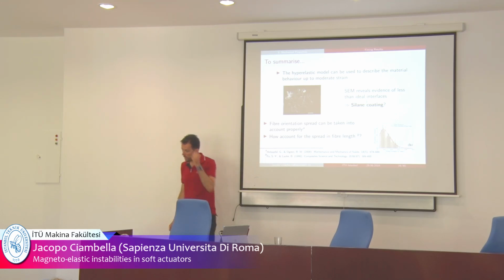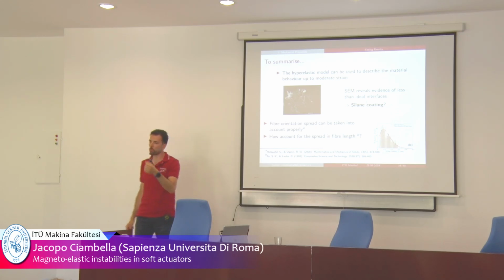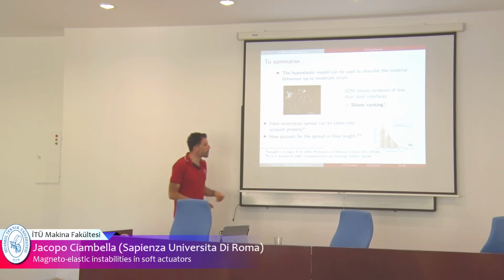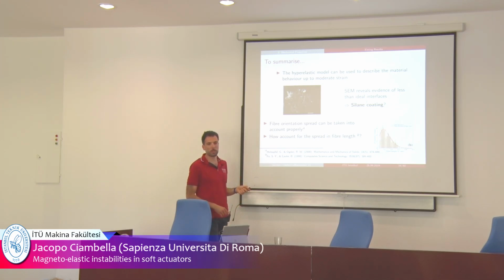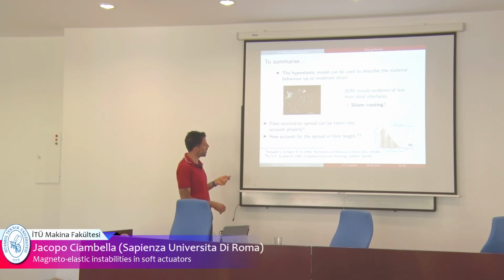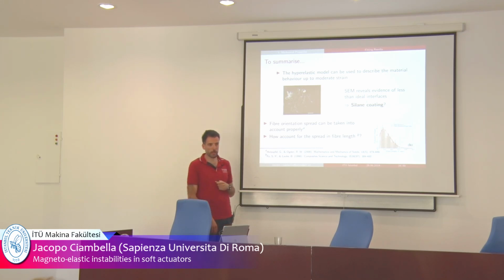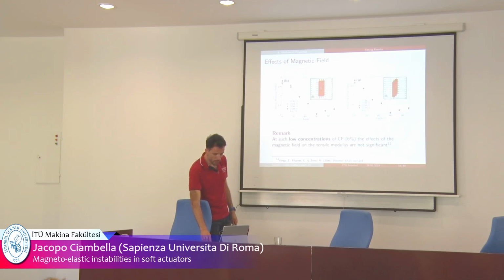When you have PDMS, you can do silane coating to improve the adhesion of the fiber within the matrix. Then of course, you can improve this model. This is a very simple transversal isotropic model. For instance, you can take into account the orientation spread within the specimen. Now there is no orientation spread, no fiber distribution. And also you can, in principle, take into account the orientation in the fiber length. This would be a nice extension of this analytical model.